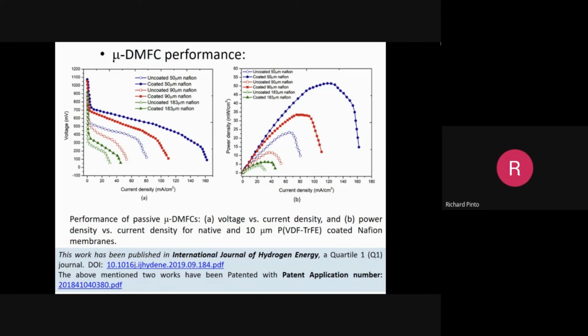So ideally 50 micron is better, provided you can reduce the methanol permeability, which you have done, as shown here. This is the coated 50 micron Nafion, and this is uncoated Nafion, 50 micron thickness. From here to here, the difference is a factor of two. So that is very, very significant. This work has been published in the International Journal of Hydrogen Energy, and we have also applied for a patent in this work. It has gone for examination now.